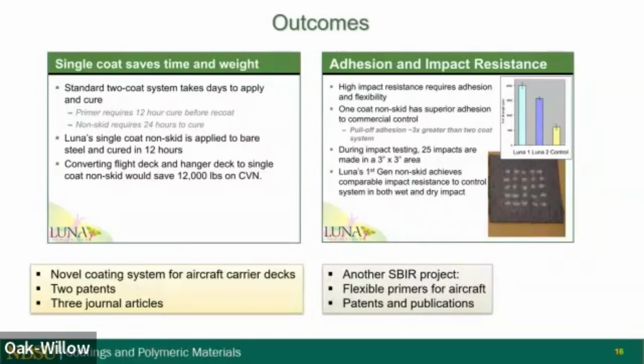And again, that was a very successful project to try to come up with a primer for aircraft aluminum that has good adhesion and is much more flexible. Next time you get on an airplane, as you're waiting to enter the door, look around and you'll see the cracks by the rivets, and wherever there are seams, those coatings tend to crack. And so if we can find a primer that is flexible enough that it doesn't crack around those seams, I think that would be a very positive thing. But we ended up with another project with them.